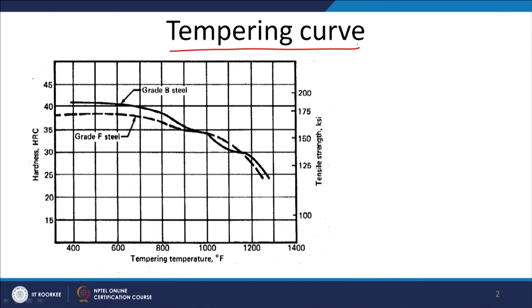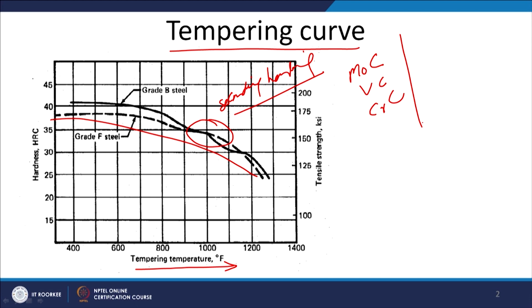Just as a quick review of the things that we talked about, the tempering behavior of the Q&T steels, wherein we have seen that as the tempering temperature is increased, there is a reduction in hardness. But at somewhere like 1000 to 1100 degrees Fahrenheit, we notice a little bit of arrest of the drop in hardness, or increase in hardness, and this is attributed to the secondary hardening of the steel, primarily due to molybdenum, vanadium and chromium carbide formation. Since these elements are already there in both these steels, there is one more aspect: the drop in hardness of the F grade steel is faster than the B grade steels, while the secondary hardening behavior is the same in both categories of steels.